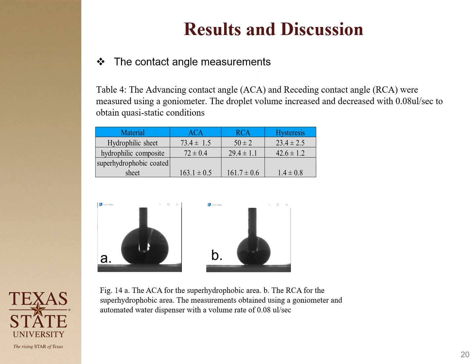The next step is measuring the wettability of the components. So I measured the advancing and receding contact angles for the hydrophilic sheet, the hydrophilic composite, and the superhydrophobic coated sheet. I created a quasi-static condition for the measurement. And you can see for the superhydrophobic coated sample that I have a really small hysteresis, which indicates that I have a Cassie-Baxter condition. So it was really superhydrophobic, and as soon as you put a droplet on it, it will move away.